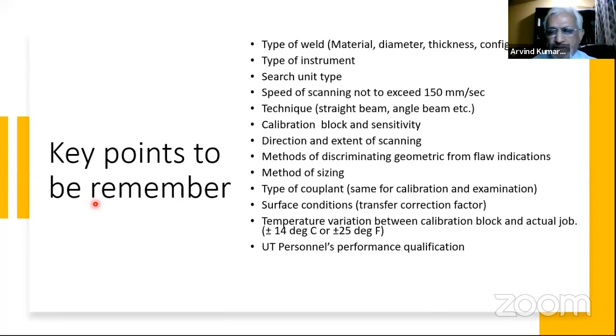Type of instrument: whether the instrument is able to pick up and is in workable condition. Search unit type, that is the probe, 60 degrees, 70 degrees, which I'm using. Speed of scanning: the code allows up to 150 mm per second, 6 inch per second. You should not go beyond that, but generally we follow much below this. Technique: whether you are using straight beam or angle beam. Calibration block and sensitivity: for guidance, you can have a look at ASME Section 5, Article 4, which gives a table, I think T434, which mentions for different thicknesses what should be the size of the hole that you can use for setting your sensitivity.